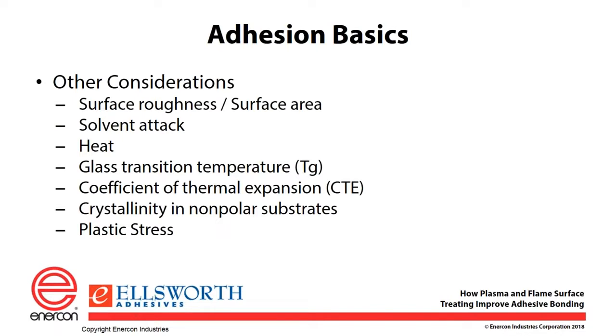Some other things that you need to consider. Surface roughness and surface area. The van der Waals forces that we were talking about when discussing plastics require contact between the adhesive and the substrate. If you have greater surface area, so say for instance you're working with a plastic that has a texture molded on the surface, that texture actually increases the surface area of that substrate versus having a very smooth substrate. That increased surface area will give you more bonding sites, which can help promote adhesion. Surface roughness, which you might get by actually abrading the surface of the substrate, also helps. This gives you greater surface area, but it also gives you areas for additional mechanical bonding where your material might dive into the substrate better.